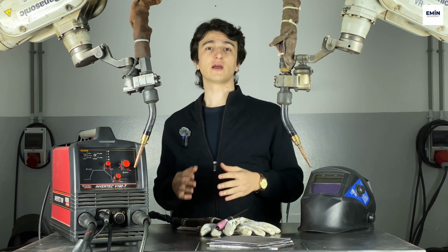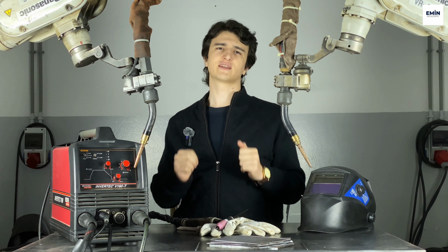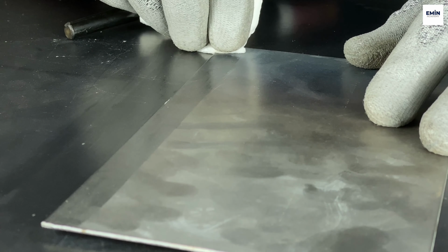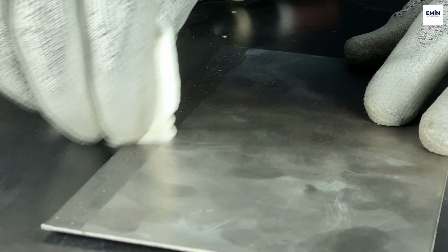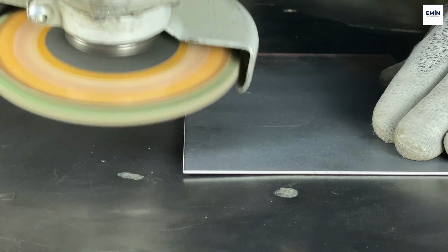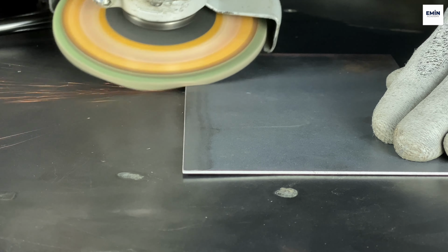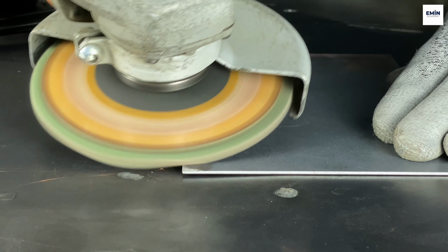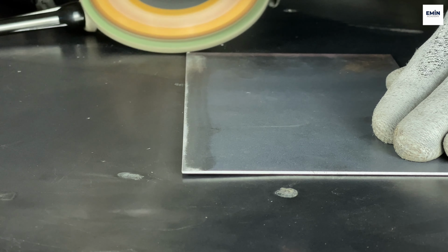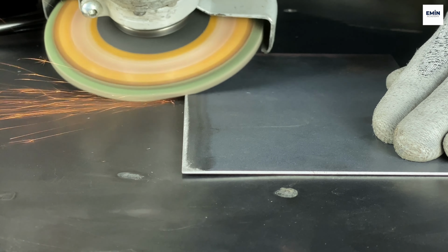In carbon steel welding, surface cleanliness directly affects the weld quality. Before welding, oil, grease, and dirt must be cleaned with acetone. If there is rust on the surface, remove it completely with a wire brush or grinding. Dirty surfaces carry oxygen into the weld pool. This causes porosity, a weak weld, and a poor appearance.